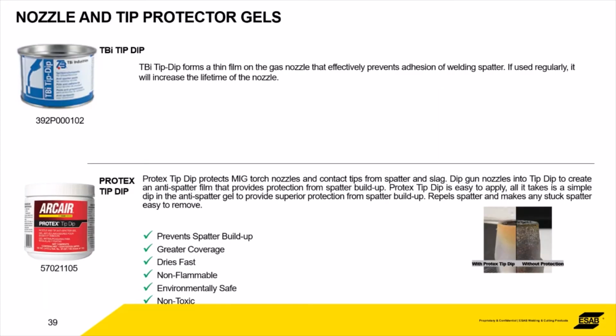Following on, talking about protecting the front end of the consumables, TBI Tip Dip. TBI Tip Dip forms a thin film around the gas nozzle, which effectively prevents adhesion and corrosion of welded spatter. If used regularly, it will increase the lifetime of your nozzles as well. So it can and does lead to increased productivity. Same again for the Protex Tip Dip at the bottom. You can see a photo of a front end nozzle, obviously used with and without our protection, and you can see the corrosion that's done once it's used without using our protection.